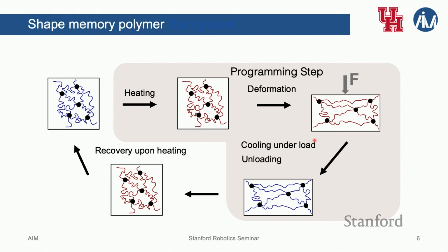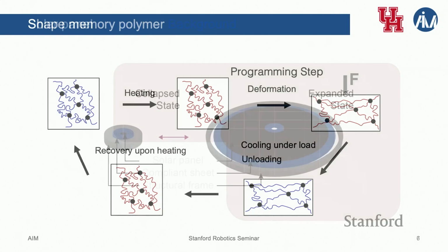So we utilize this to autonomously deploy that solar panel you just saw. So that's the mechanism. And of course, you can point out the obvious issue with this. You can only do this once, right? Once it recovers back to the original shape, you will need to reprogram it in that step we highlighted in pink to achieve a second recovery. But that's the notion of how we use this inherently locked-in pre-strain to exhibit autonomous change of shape.